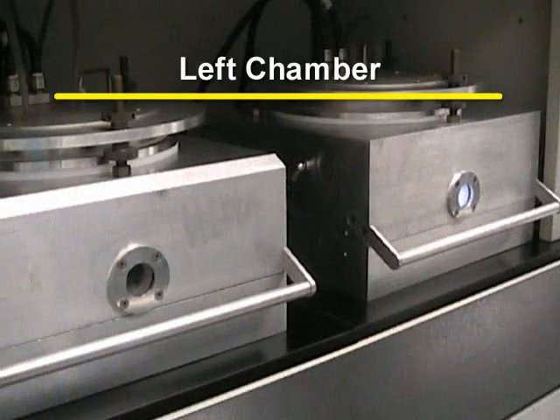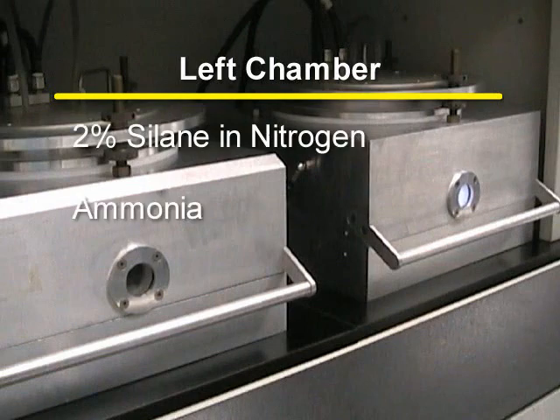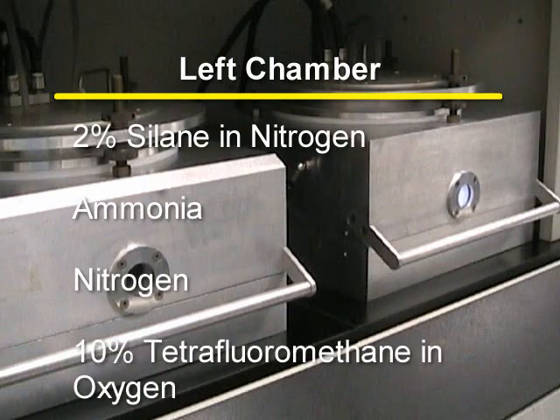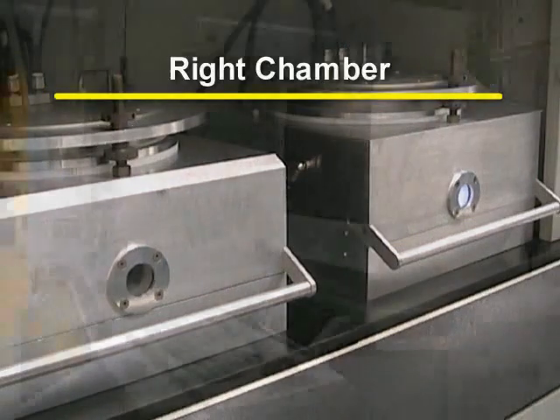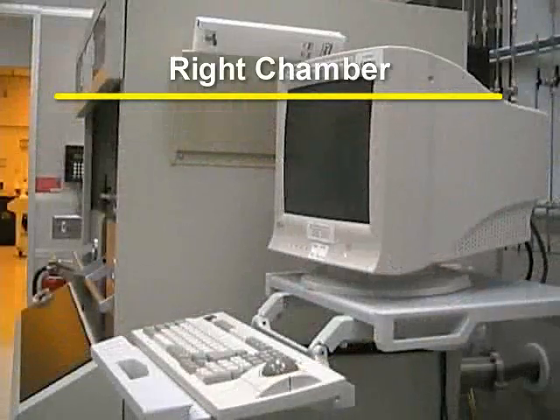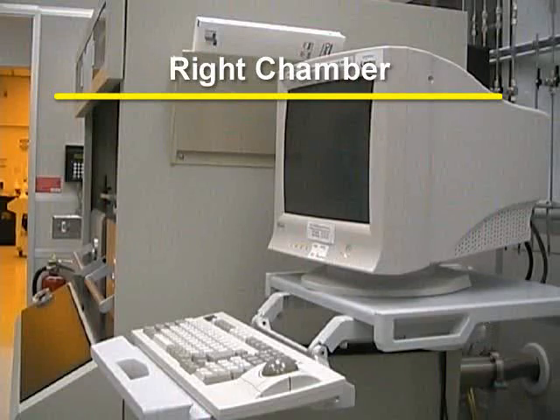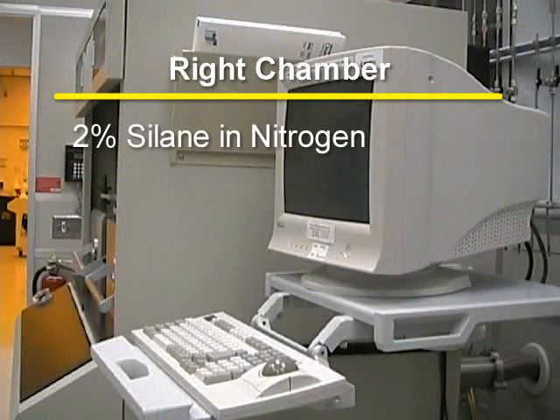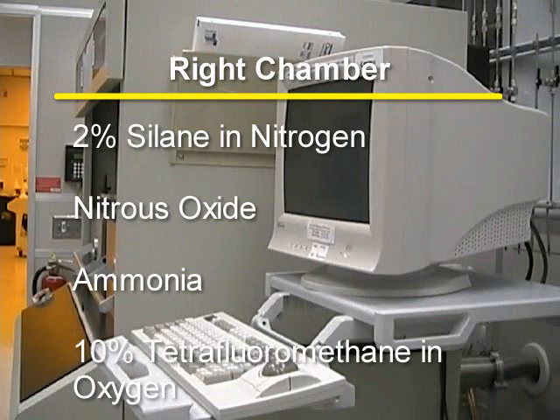One is intended for silicon nitride depositions and has 2% silane in nitrogen, ammonia, nitrogen, and 10% tetrafluoromethane in oxygen connected to it. The other chamber is intended primarily for silicon dioxide depositions and is connected to 2% silane in nitrogen, nitrous oxide, ammonia, and 10% tetrafluoromethane in oxygen, which is used for cleaning the chamber.